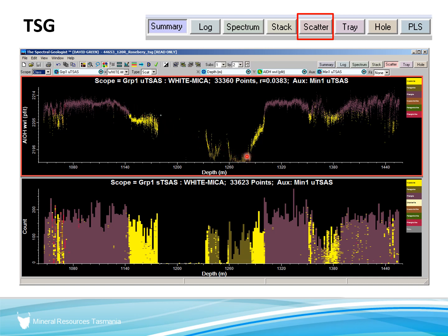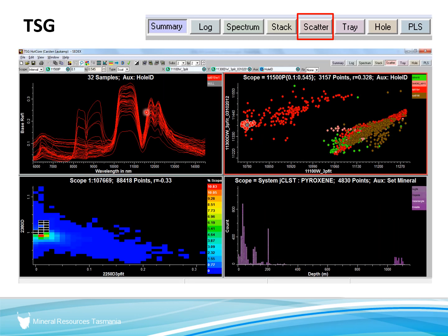The short wavelengths are more aluminium rich, more end-member white muscovite, and the longer wavelengths more phengitic, magnesium, iron, silicon richer. Things can be presented as histograms. We can stack spectra, we can show density diagrams, all sorts of things are possible in scatter diagrams.